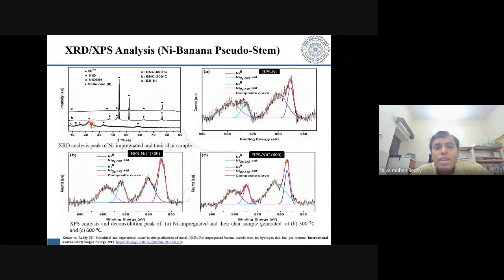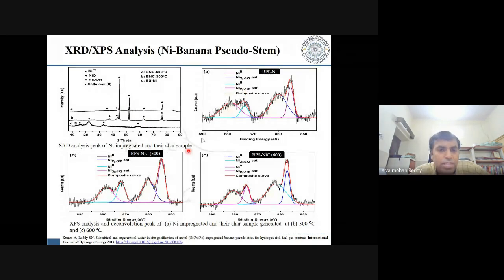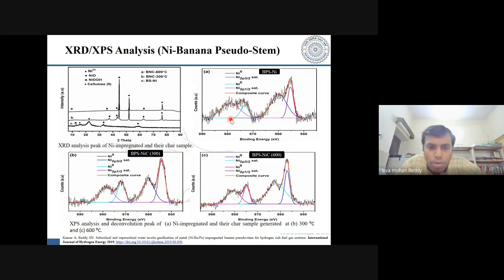So this conveys that when we increase the temperature from 300 to 600 degrees centigrade during the hydrothermal degradation, these metals are reduced from the oxides in the +2 oxidation state, which are present in the metal impregnated biomass at normal room temperature and at 300 degrees centigrade. So these get converted into active nanometallic forms. Okay. Now the same thing has been observed with our ruthenium also. When we impregnated ruthenium, we have a sharp peak of active ruthenium formed around 39 degree of 2 theta.